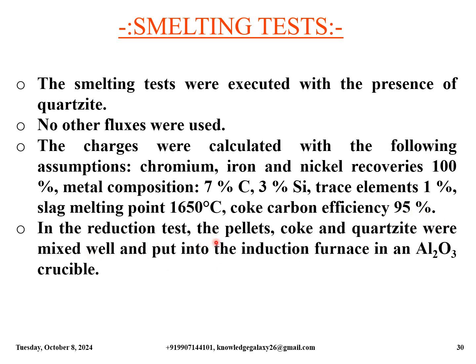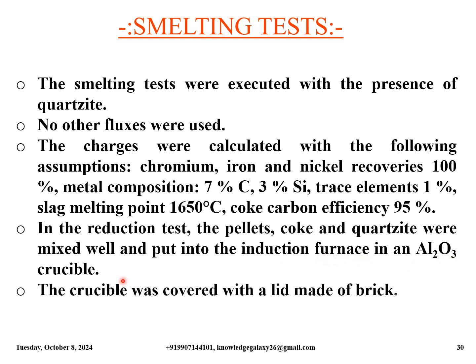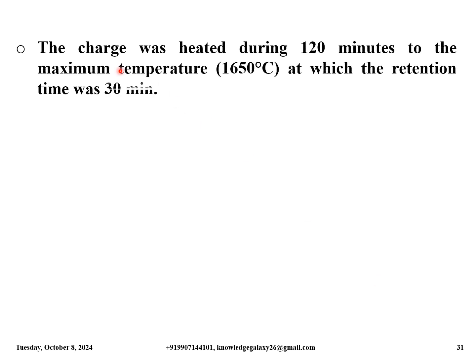In the reduction test, the pellets, coke and quartzite were mixed well and put into the induction furnace in an Al2O3 crucible. The crucible was covered with a lid made of brick. The charge was heated during 120 minutes to the maximum temperature of 1650 degrees Celsius, at which the retention time was 30 minutes.